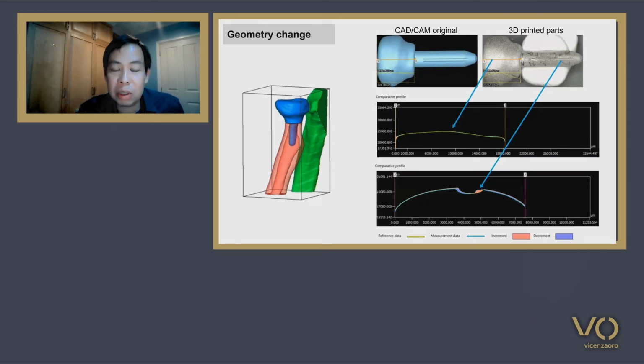For the geometrical change, we also use a laser interferometer to check the change in the height and the curvatures. And as you see here, the scans were performed on the head of the elbow joint and also on the stem side. So you could see that there is a little bit of variation on the stem side, in the order of tens of microns, that we still have to fix.